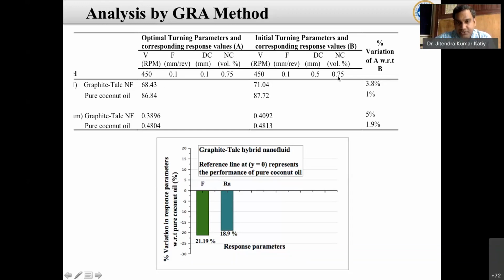But in case, randomly, I select another parameter in that particular one. Maybe that will also be there, because this GRA integrity can reduce the experiments. So that is a confirmation test also, to see whether that is a correct observation or not. So I performed this confirmation test, and observed that the confirmation test and the optimal test obtained by the GRA are within the range of 1 to 5%, which is an acceptable range. And further, in terms of the surface roughness also, we can get it in that particular range.